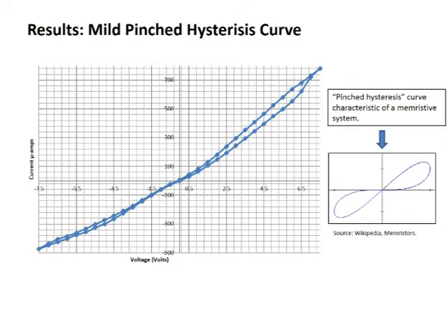The 8 cells I tested did exhibit some level of memristive behavior, but the results were not very compelling. The difference between the high and low resistance values was very small, and the endurance of the device, or the number of times it could be cycled, was rarely more than 2.